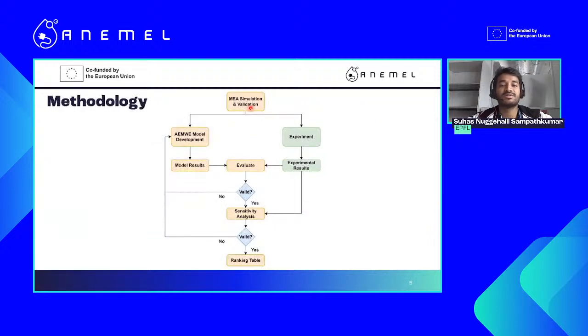So in our methodology, we developed a small model, 1 cross 1 centimeter, and ran it with coupling of computational fluid dynamics and electrochemistries, and then we evaluated this with the experiments. And if the model had a close tolerance with the results, we moved further on to the sensitivity analysis, and then we arrived at a ranking table trying to map all these performance-affecting parameters.